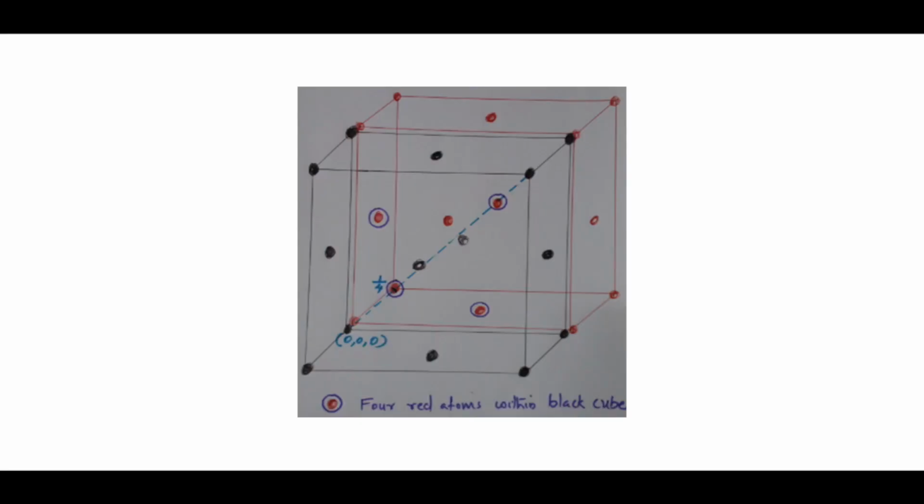One face-centered cubic Bravais lattice is pushed along the main body diagonal by 1/4, 1/4, 1/4. So in the case of diamond cubic crystal structure, there are two sets of lattice positions. These two sets of lattice positions associated with two different face-centered cubic Bravais lattices are chemically identical, but not equivalent. That is what we have seen. Chemically identical means all these lattice positions are attached with the same atom. In diamond, all are carbon atoms. If it is a silicon crystal, all are silicon atoms, or germanium atoms. So these lattice positions are chemically identical, but they are not equivalent.